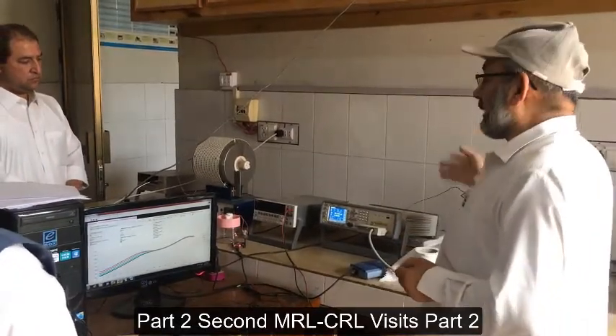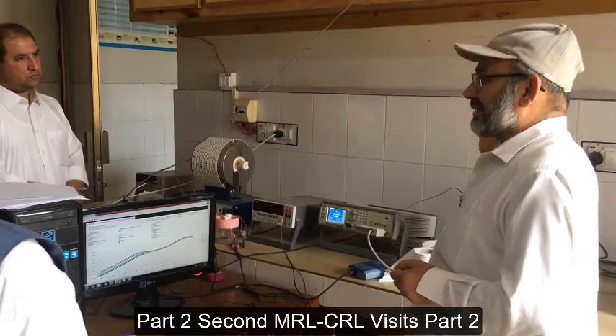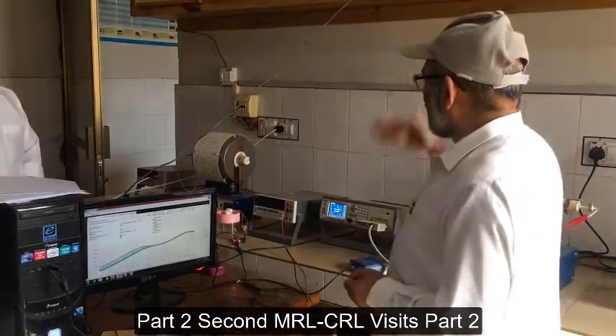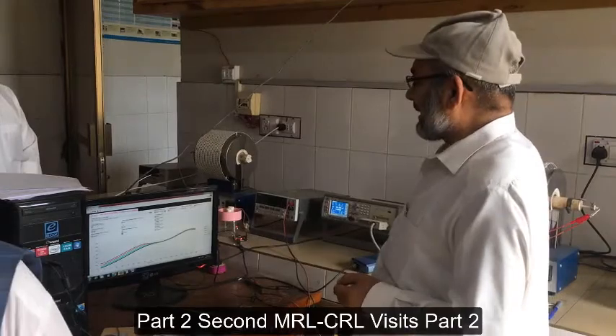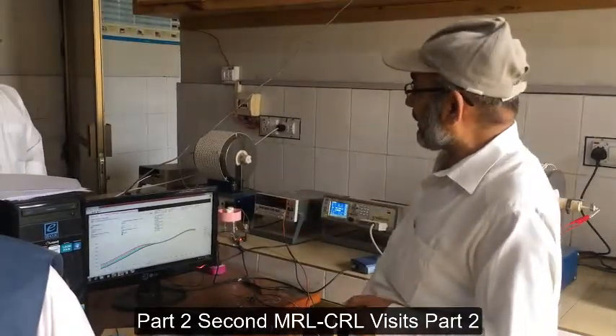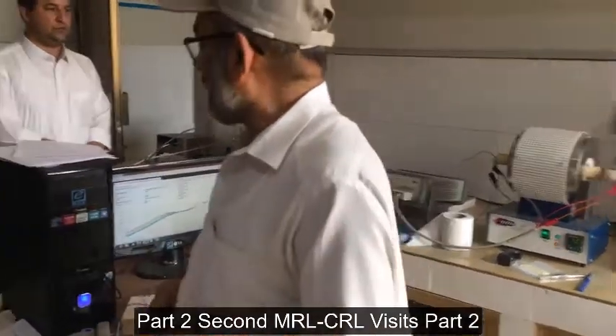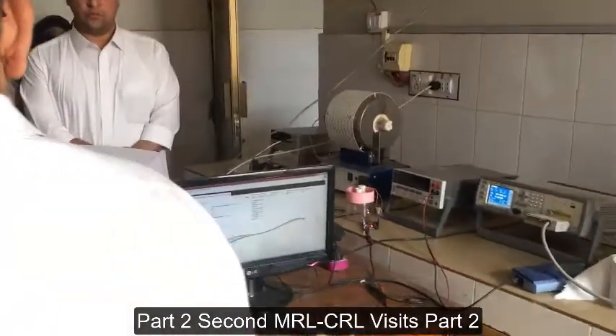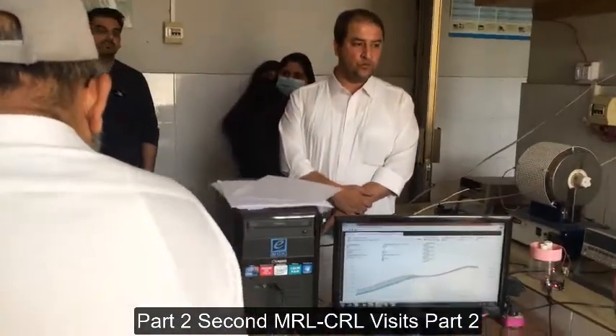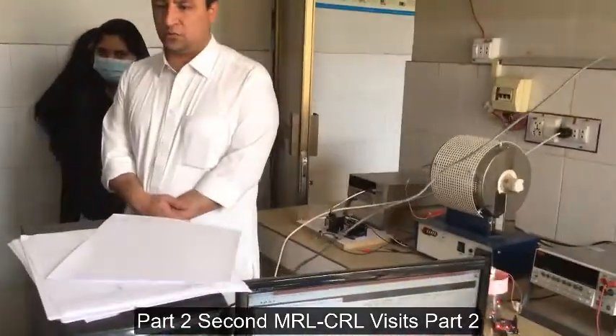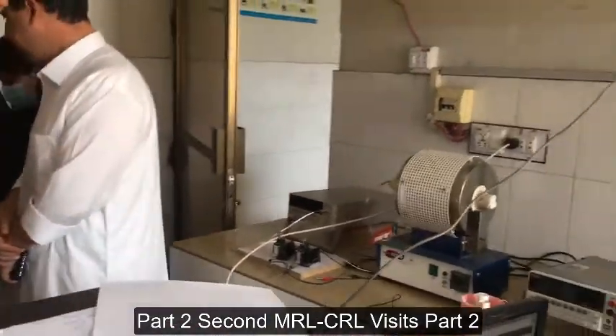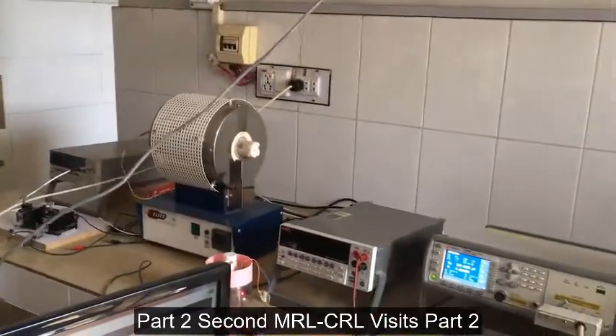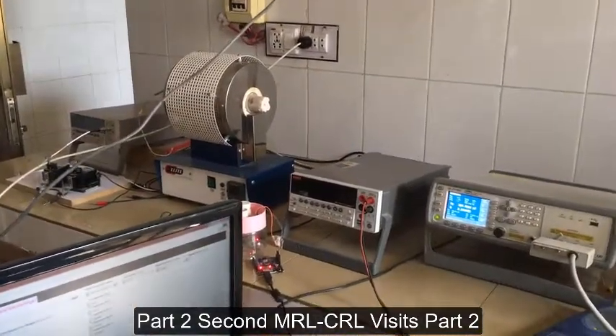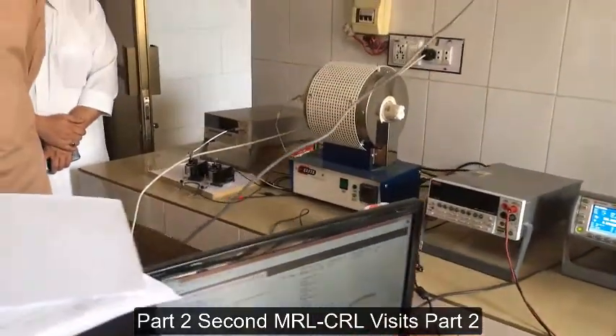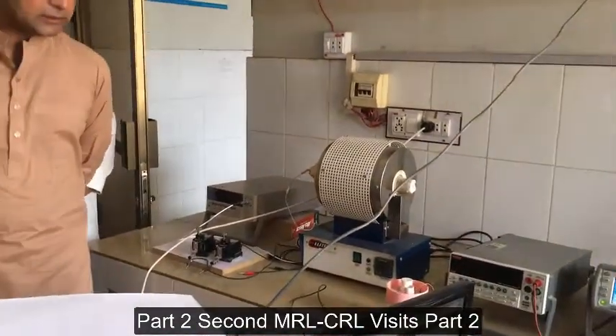This machine is measuring the loss and the dielectric constant of the material, and you can increase the dielectric constant and decrease the size of the circuit, and we plot it here. It tells us about the Curie temperature as well, at which temperature the polarization is maximum and the quality of the material is best for a particular application. There are also some source meters and nanovolt meters which measure the IV characteristics, current voltage characteristics, of various materials. So they are mostly related to physics.